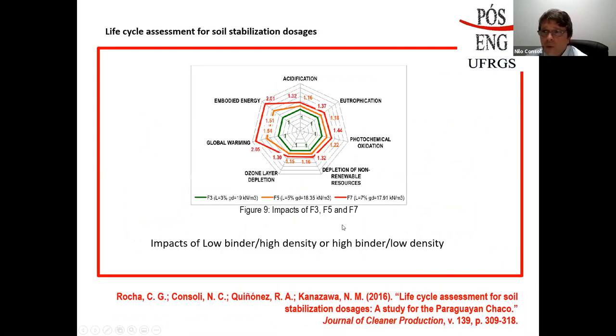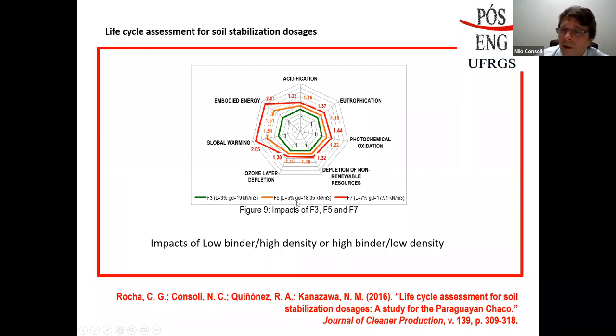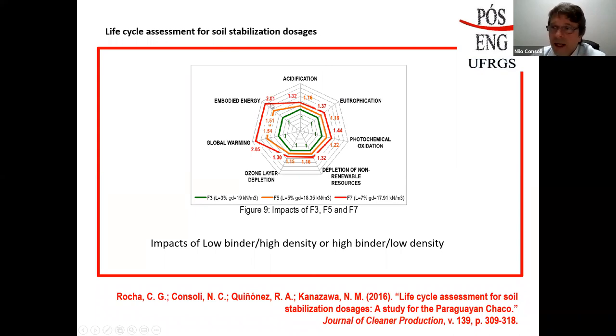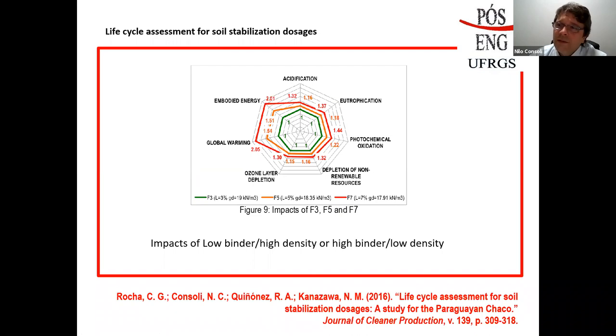We also performed life cycle analysis from an environmental viewpoint. For a given target strength achieved through different binder amounts and densities, a more environmentally sustainable result — regarding global warming and embodied energy — is obtained by compacting more rather than adding more binder. So achieving a given strength by increasing dry unit weight rather than increasing binder content is better both environmentally and economically. Published in Journal of Cleaner Production in 2016.